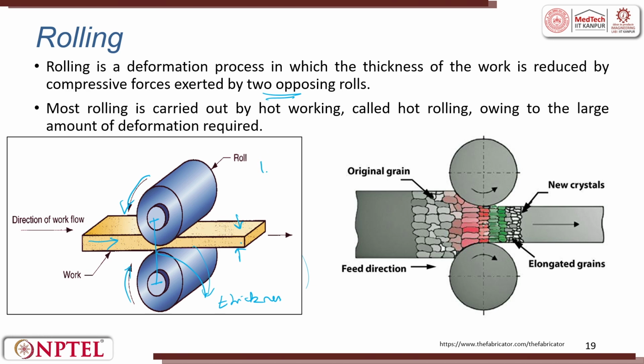First time we roll from 1 millimeter to 0.8 millimeter, then from 0.8 to 0.6 millimeter, then 0.6 to 0.5 millimeter, then to 0.4, then we go up to 0.3, then 0.2, then 0.15, then 0.12, and finally 0.1. So, all these things are in millimeter. We go multiple steps, right. Multiple steps means each time the metal is out, we try to reduce the thickness, then feed it inside.